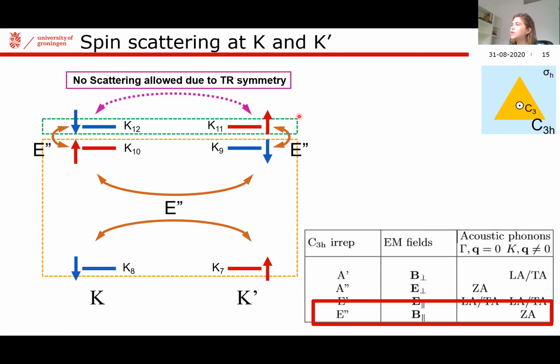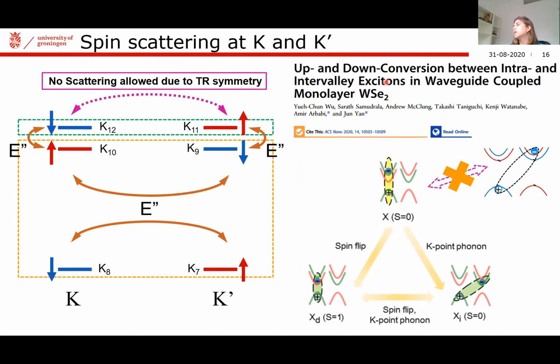And that actually matches very well some recent experimental results in this work that was just published this summer at ACS Nano, where they look at up and down conversion processes between the various exciton species. And what they find is that, although they see various conversion processes going on, they never see any evidence of this conversion process that I highlight here with this arrow, where we transform a bright exciton into an inter-valley bright exciton. So this is very much in line with our conclusion here that this scattering is protected by time reversal symmetry.